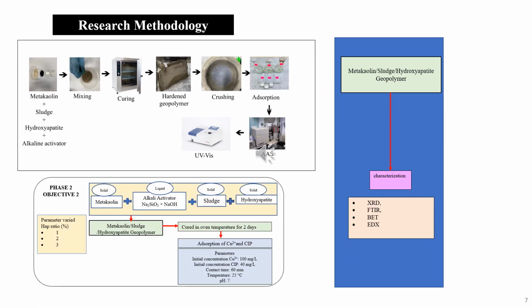For research methodology, it starts with mixing of raw materials such as metakaolin, sludge, and hydroxyapatite with alkali activator. Then the obtained geopolymer paste was oven cured at 60 degrees Celsius. After that, the hardened geopolymer was crushed into powder particles to be directly applied in the adsorption process. After adsorption, the concentration and removal efficiency of copper and ciprofloxacin was measured by AAS and UV-Vis respectively. For characterization, the synthesized geopolymer was characterized by XRD, FTIR, BET, and EDX.